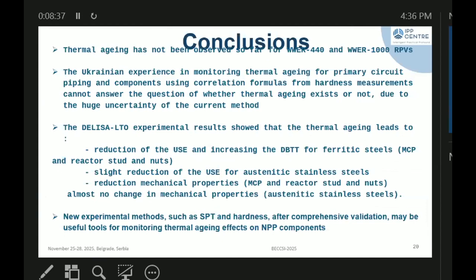And conclusion. The main result is that thermal aging leads, first, for ferritic steel, to a reduction of upper shelf energy, an increase in the ductile-to-brittle transition temperature, and a decrease in mechanical properties. And for austenitic stainless steel, it's a slight reduction of upper shelf energy and almost no effect on mechanical properties.